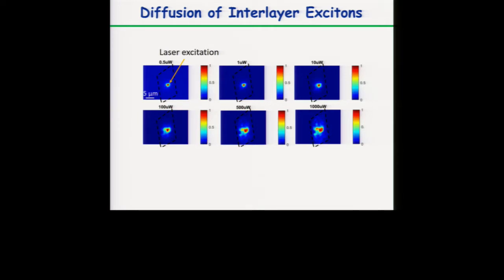And at the end, what they do is they move. They are mobile. They have long lifetime, so they can go to different parts of the sample, even where we are not shining, even 10 micrometers away. We are not directly shining a laser on them, right? So we can get interlayer excitons even farther apart. As I say, we are collecting from different spaces while fixing the excitation.